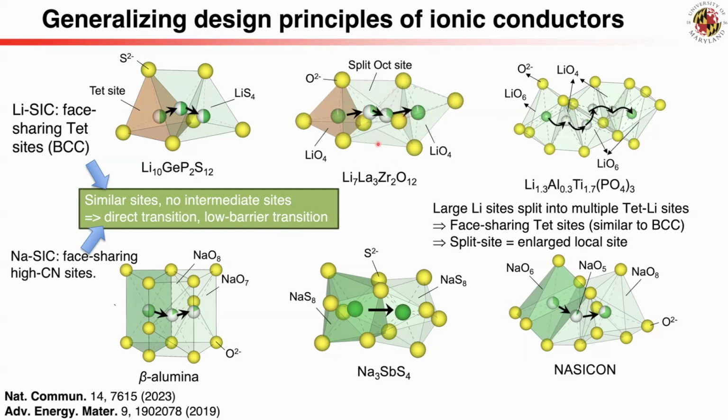In addition, this large site was also reported in our previous paper to improve lithium disordering. We also find that site distortion plays an important role. Previously, site distortion was reported to promote lithium disordering. Here we find that having the distortion would actually enlarge the bottleneck, as observed in many of these sodium conductors. So that's another good feature of site distortion, commonly observed in these superionic conductors.